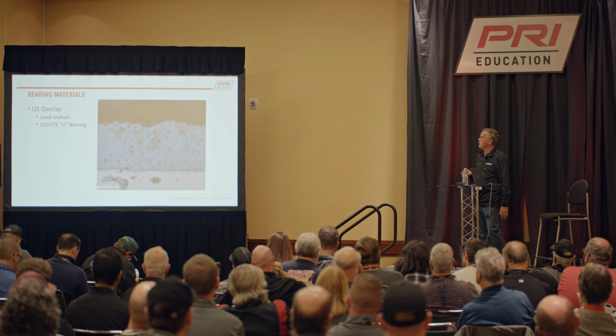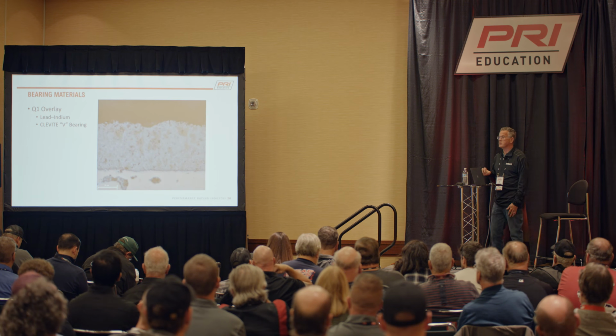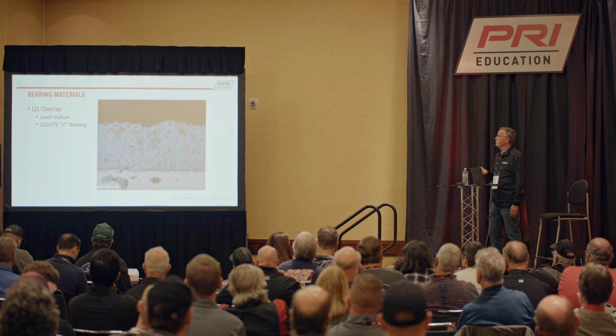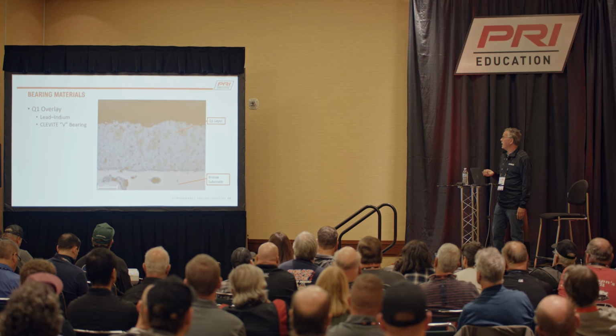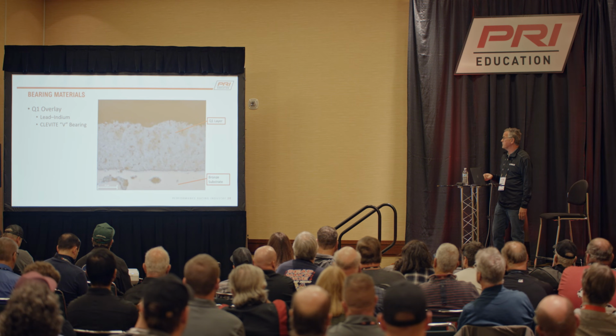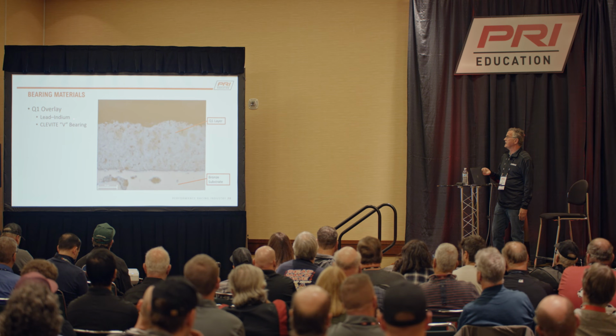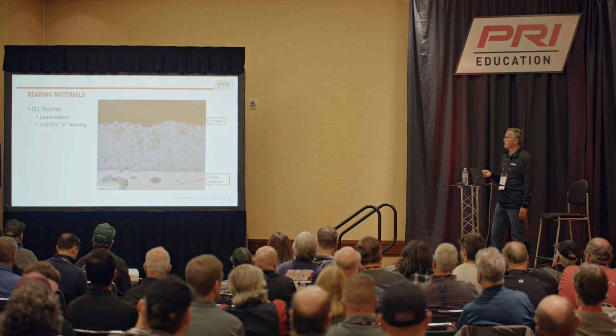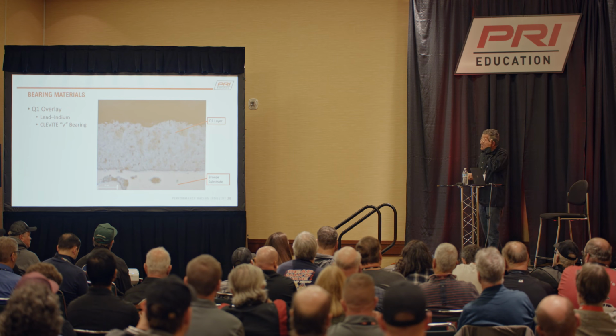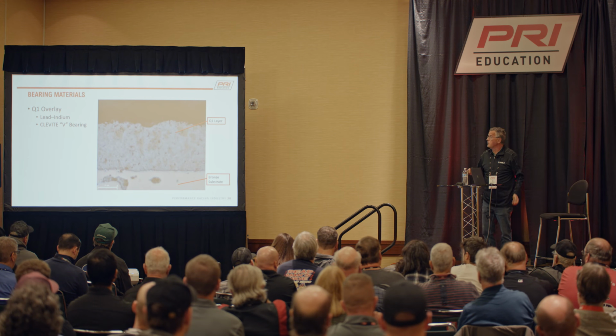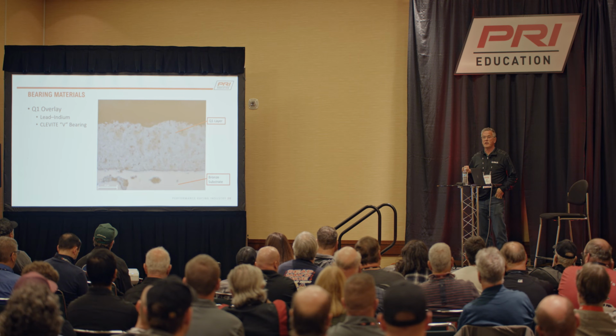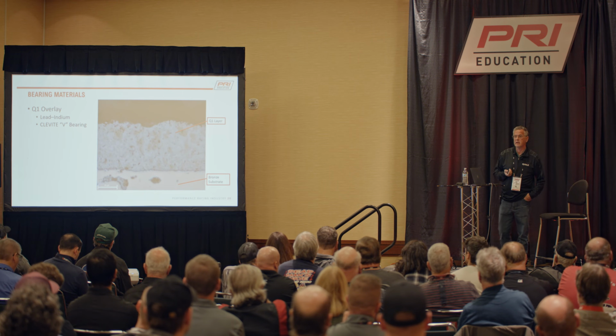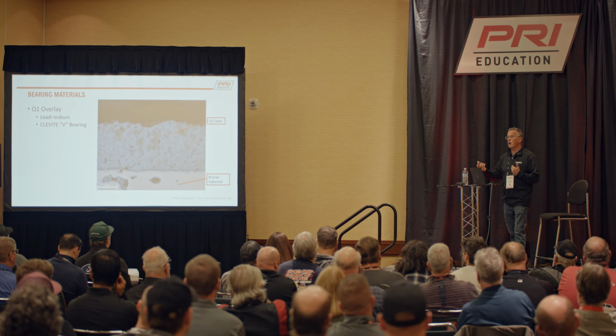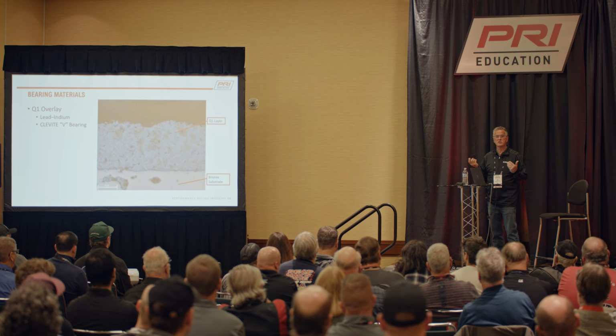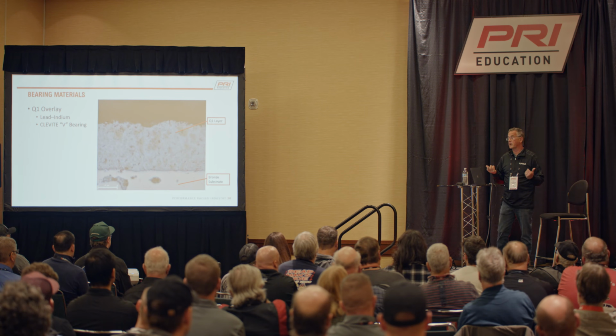So the difference, if you get into a higher performance application, Clevite has the V series, which is a lead indium. It has the same bronze substrate, and it is a lead indium straight on top of it. Lead indium doesn't migrate. So the difference is the H bearing is a harder bearing, and it will give you more service life. The lead indium is a softer bearing. It doesn't give you as long a service life, okay?